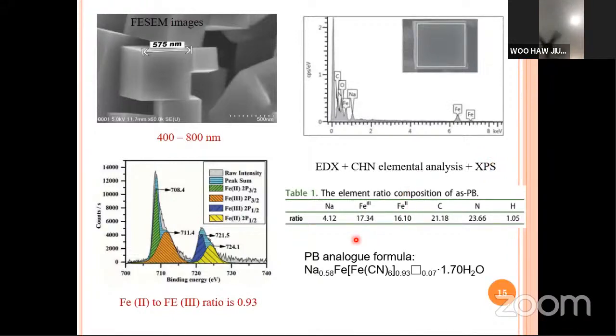As tabulated in Table 1, the element ratio composition of our product. With this, we use the atomic weight, divide it and normalize it to Fe3+ to obtain the PB analog formula as given here. So we have sodium 0.58, Fe3+, Fe2+ (CN)6 0.93, with a vacancy value of 0.07 and an interstitial water of 1.70. This is considered quite a good result because we have a quite low vacancy amount here, 0.07, and we were excited to test the electrochemical performance in a sodium-ion battery.